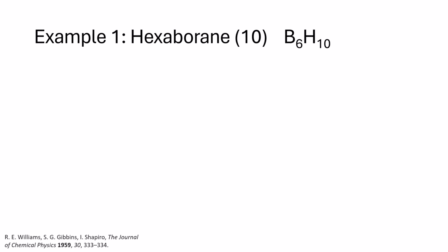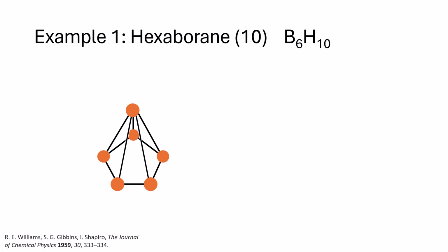The first example of boron structure determination by NMR that we will examine is hexaborane(10). Based on crystallographic evidence, it was proposed that hexaborane(10) had this pentagonal pyramidal structure, with 1 apical boron atom and 5 basal boron atoms. Each of the boron atoms is part of a BH subunit. The 4 remaining hydrogen atoms act as bridging hydrogens along the base.